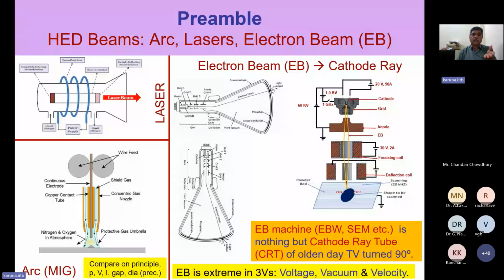Okay, and the same electron beam concept is used in SEM, scanning electron microscope. There, the beam is of the order of microns, 10 microns, 12 microns. And the beam can be deflected onto the sample at something like 1 lakh meter per second. Now think of the magnitudes. In the arc case, the torch speed cannot be more than about a meter per minute. Whereas in laser, the scanning speed using galvanometer can be of the order of 100 meter per second. So 1 meter per minute versus 100 meter per second in the case of laser. Whereas in electron beam, for scanning electron microscope, the speed is 1 lakh meter per second. And for our additive hybrid manufacturing applications, it is 10,000 meter per second.